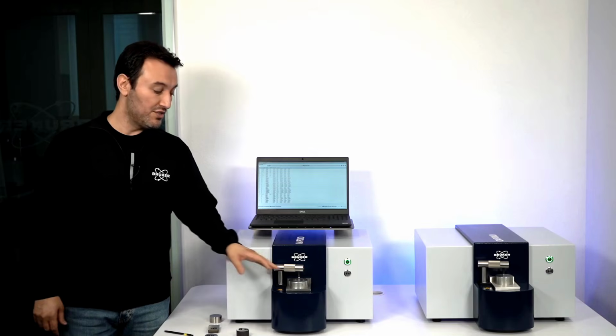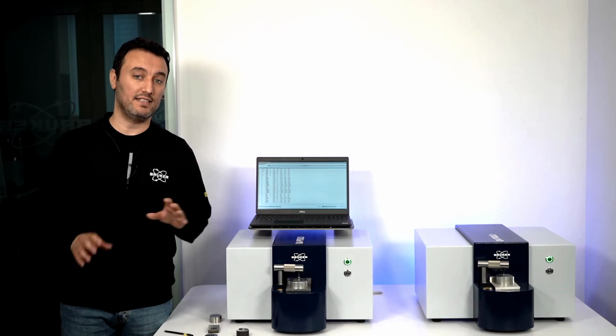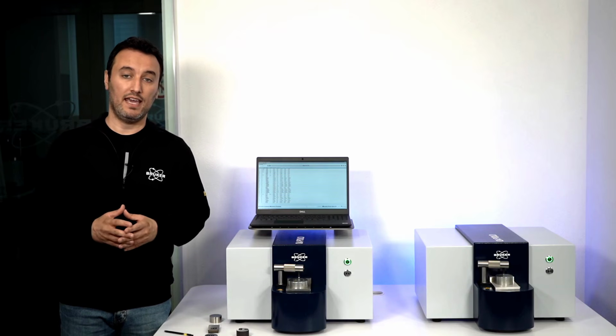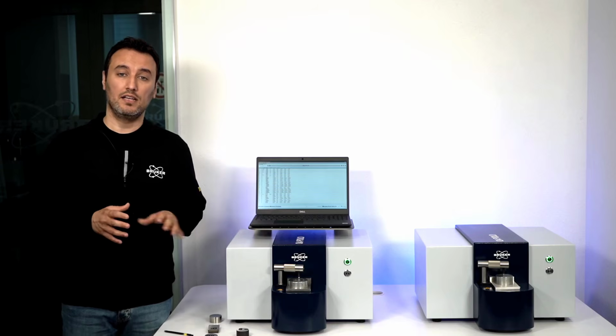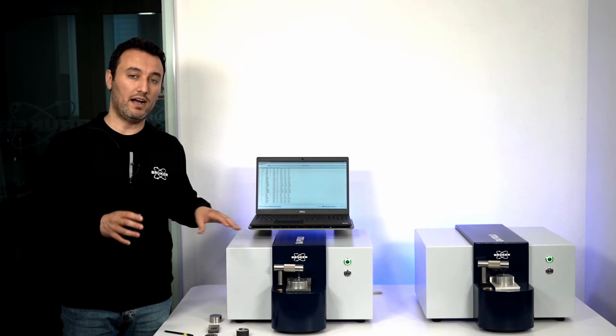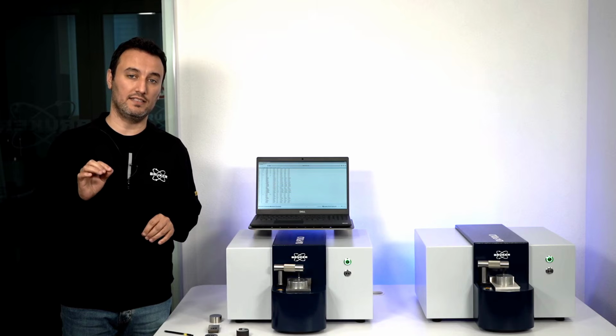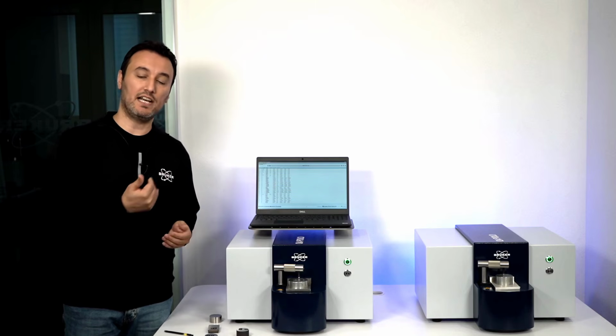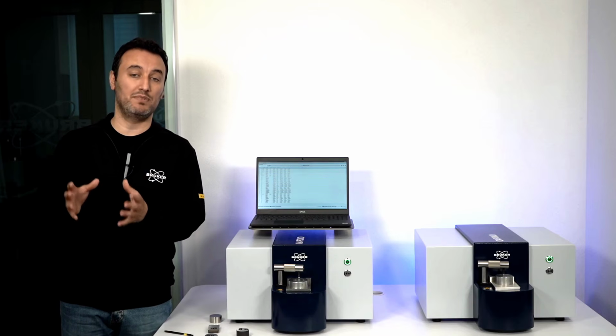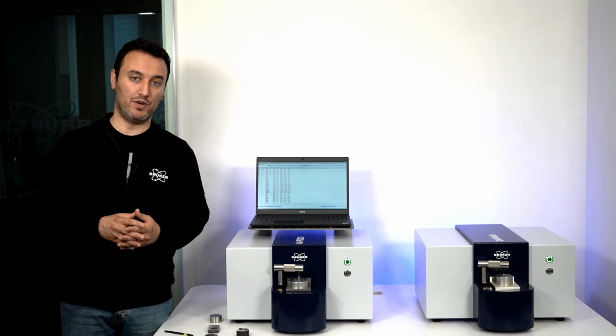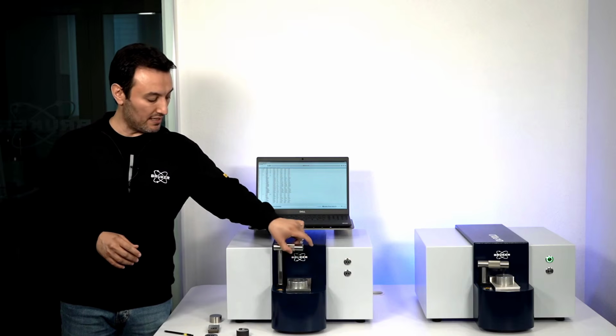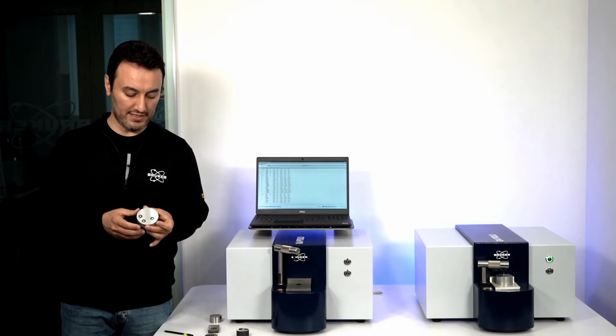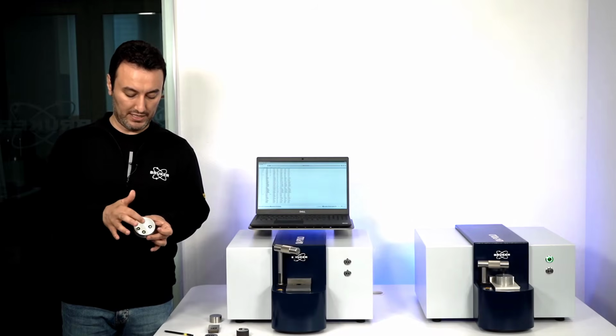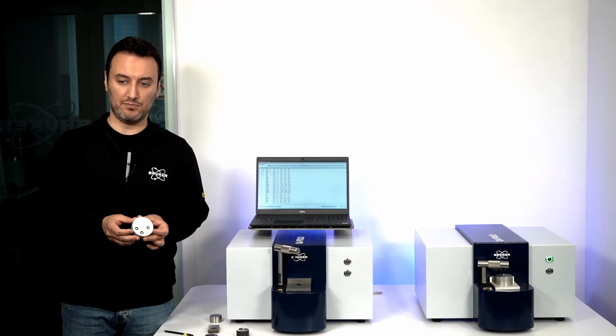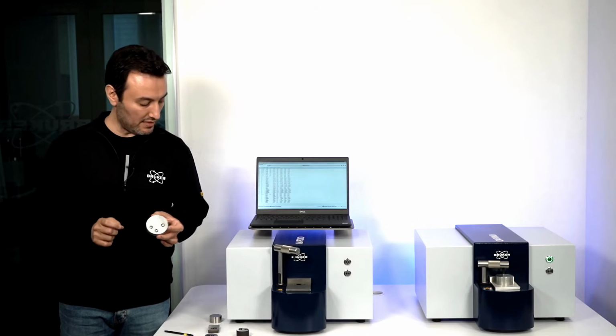All right, so this high silicon aluminum sample was the last one that we analyzed today. And in the Elemental Suite, we saw that Q4 POLO did a very highly precise, accurate analysis on this aluminum sample. We also saw that the results we got at the end of the analysis actually matched pretty well what is specified by the grade. So again, let's take our sample and have a look at the sample surface. We have pretty well burn spots on the sample surface with black circles around them.